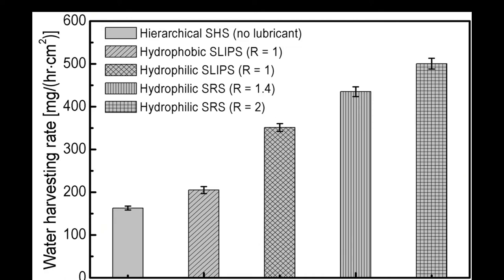As you can see, quantitatively we measure how much water can be collected by slippery rough surface, and as I mentioned earlier, at our lab scale it can reach about 120 liters of water per square meter per day, which is about an order of magnitude higher than the typical bulk harvesting material that can collect water daily at this point. Yeah, that's stunning. That's amazing that by manipulating the materials, the surface chemistry and the surface morphology, you've managed to get that level of improvement in this particular dimension of water harvesting. This is nature-inspired nanotechnology work at its best.